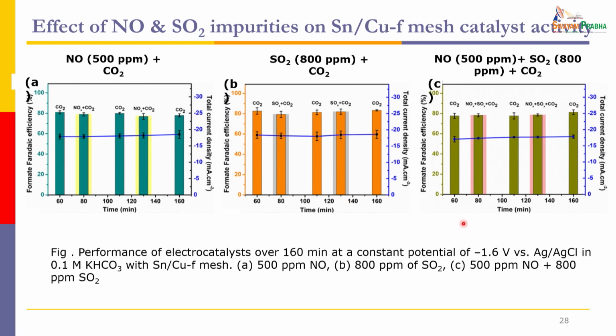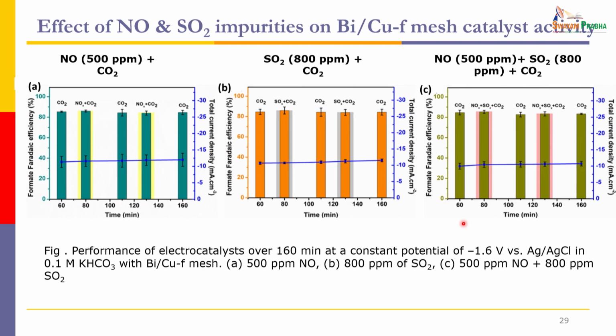And in most cases, you can see there is no change in the top value. So it is within the error bar. You can see it's all about 80% Faraday efficiency, where 80% of your current is utilized to convert carbon dioxide into formic acid. And so there is no change. This is for the tin catalyst, and we did the same for bismuth catalyst. So bismuth also gave a very similar performance. So we were able to get two catalysts with very similar performance.